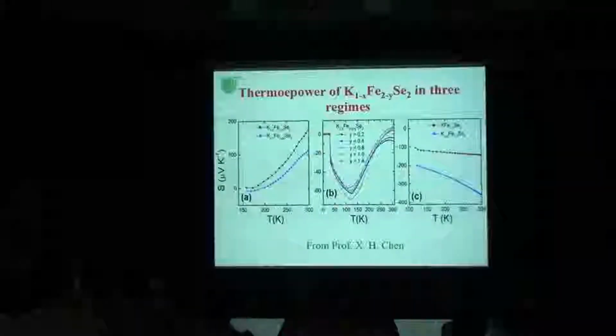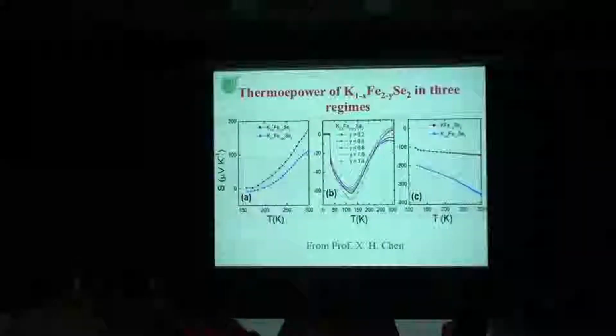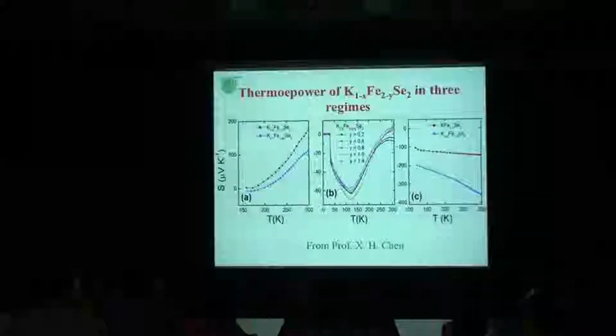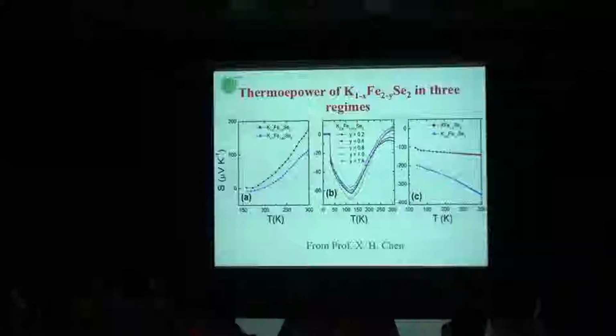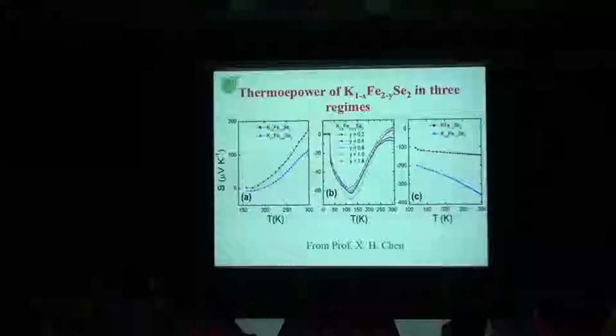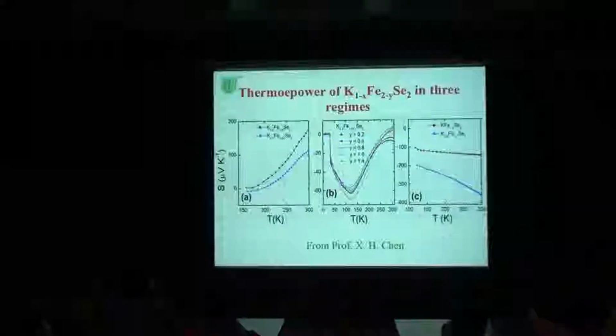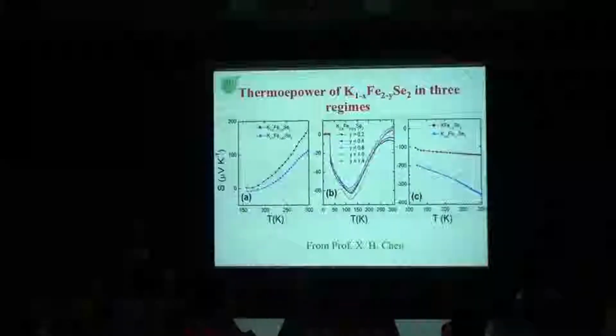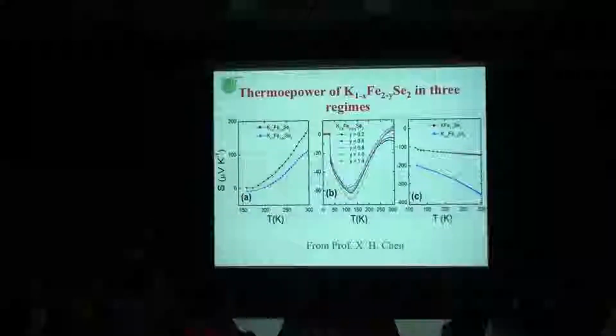And that is another system. This was a much later discovery in China. Basically, it's a follow-up of our work on iron selenide: they put some potassium in between the layers, stabilize the phase, and get superconductivity. For the composition that becomes superconducting, you see those maxima here. For non-superconducting, you don't see it. So that tells you this is something really important. Experimentally, we have to identify what that is, and theoretically, we also need to learn more about what is going on here.